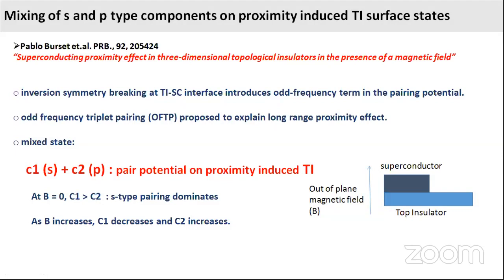There is an S-type pairing potential, and then there is a P-type pairing potential with their respective strength coefficients. The paper discusses that at zero magnetic field, it is the S-type pairing that dominates. C1 is much greater than C2. There is a presence of P-type as well, but the S-type dominates. And as B increases, C1 decreases and C2 increases. At a magnetic field strength which approaches the chemical potential of the induced superconductivity, there is a flipping that happens. The P-type becomes more dominant than the S-type. So, that means we can expect some kind of change in the induced superconductivity observed on the TI as we increase the magnetic field strength. That's what we expect.